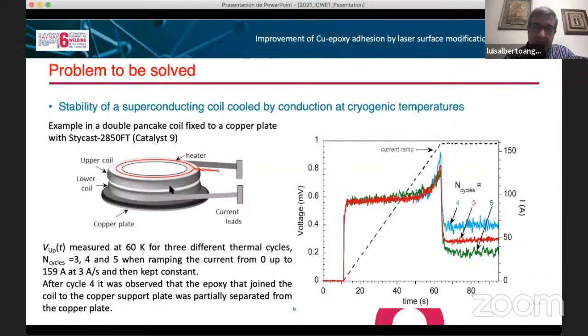So this experiment we have been repeating several times. You see, for instance, that after 3 times, this is the level of voltage you have on the coil. After the 4th cycle, we observe that this voltage increases. This could be because we have some problems on the coil that started to be degraded due to the thermal cyclings. And this is important from the superconducting point of view.